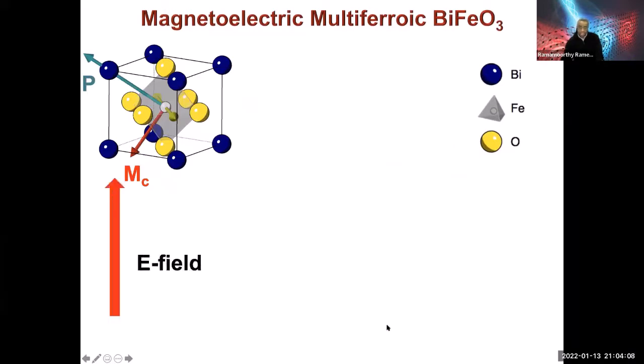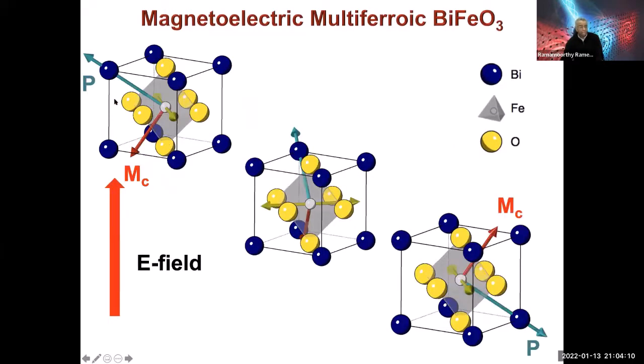Now, I think I mentioned this: when you switch the polarization, this green arrow, by 180 degrees, what happens to this canted moment? Some of the original work said nothing should happen. That's a symmetry operator. So the canted moment could be this way. Now, Jorge was saying, guys, that's not true, because the polarization does not do the classical Vanderbilt switching. It doesn't go through the high symmetry state and then go to the other direction.